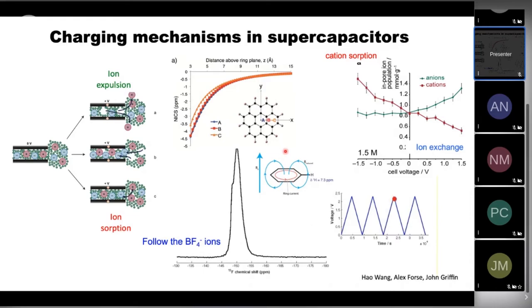And if you live on top of a benzene ring, you have a negative shift. If you live in the same plane, you have a positive shift. And so this shift to the right is due to the ring currents. And then when we charge the supercap positively, we inject holes into the system and it becomes less aromatic and it shifts to the left. So we can understand the mechanisms for the NMR signal.